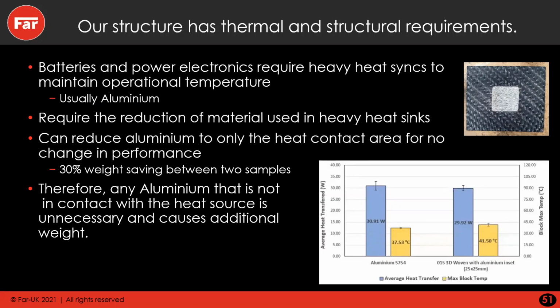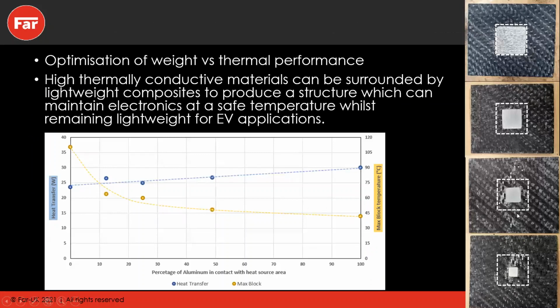in the surrounding structure. For this case study, we've ignored galvanic corrosion, but in reality, you could use carbon and copper or glass and aluminium, and you'd get the same results. So now that we know we only require thermally conductive material to be in contact with a heat source, we can look to optimize that further.